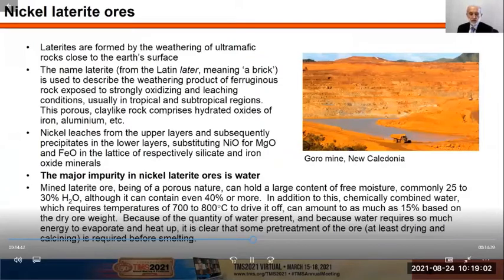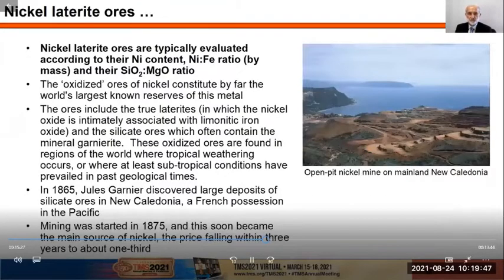It's very important to note that the major impurity in nickel laterite ores is in fact water. Mined laterite ore, being very porous, can hold a large content of free moisture, commonly 25 to 30%, going up to even 40% or more. In addition to this, chemically combined water, which requires temperatures of up to 800 degrees Celsius to drive off, can amount to as much as 15% based on the dry ore weight. Because of the quantity of water present, and because water requires so much energy to evaporate and heat up, it is clear that some pretreatment of the ore, at least drying and calcining, is required before smelting.